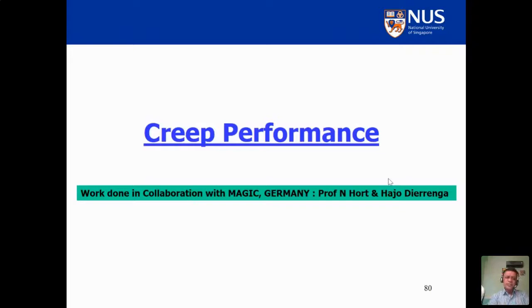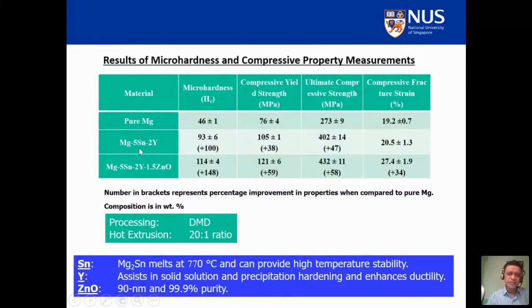So let's look at the deformation of material under high temperature, which is called creep. This work we did in collaboration with researchers in Germany, at the Magnesium Innovation Center. We gave them the material with tin and yttrium, and you can see again, our alloy had a better hardness and a better compressive yield and compressive strength and similar ductility. And when we put zinc oxide in there, again we get more improvement in the strength. Our yield strength also goes up. Our ultimate compressive strength goes up. And in this situation, our fracture strain also got to 27.4%, which is much higher than many commercial aluminum alloys. So that means this material is fabricable.